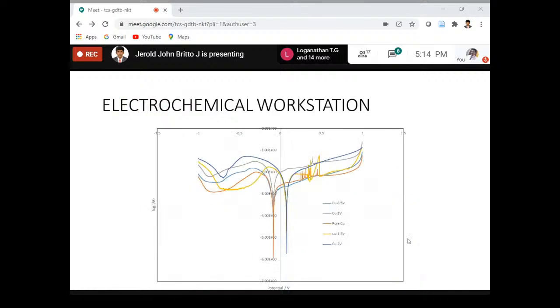After that, I have gone for corrosion testing. First I used the electrochemical workstation, in which three different kinds of electrodes are there. Platinum is used as the counter electrode, calomel is used as the reference, and the working plate, whichever composite specimen I have produced using stir casting, is used as the working electrode. Using the three electrodes, I have done the electrochemical testing, and after that I got this result.